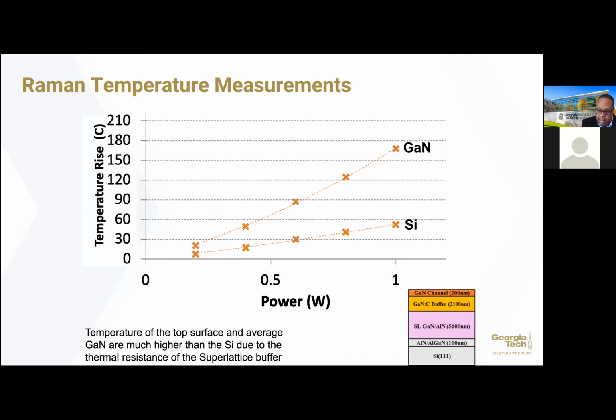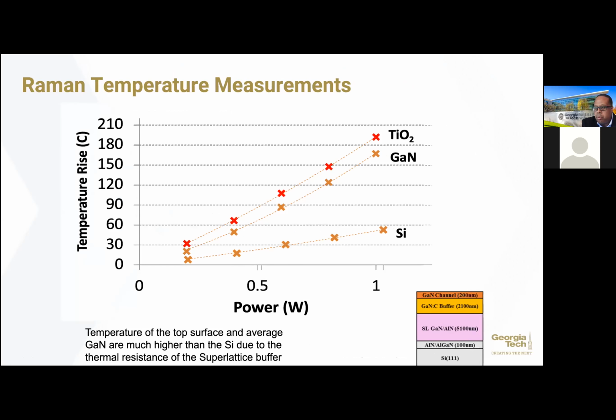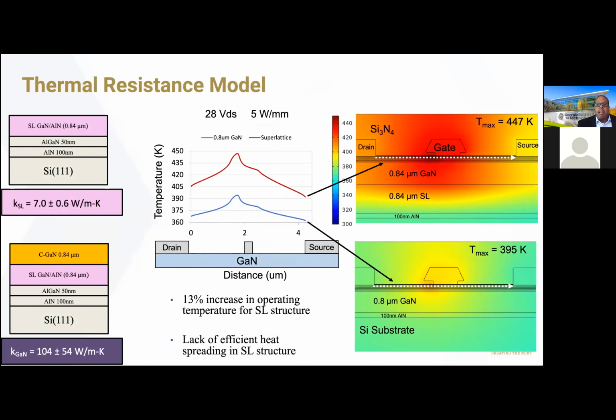When I look at the top temperature of the TiO2, this is what you see. Again, the temperature at the very top is slightly larger than the average temperature, which is what we expect to see. But there's this huge drop between the gallium nitride and silicon, and we believe that's coming from this superlattice structure. So, going through and doing modeling and some measurements, in this case we measure the thermal conductivity of the superlattice structure. You can see that it has a very low thermal conductivity, on the order of 7 watts per meter K.